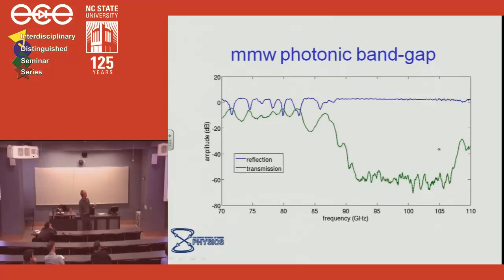Okay? This is a logarithmic scale. So that's as close to a perfect reflector as I can measure. And the transmitted field is down by 60 dB. And this is entirely due to multiple scattering. Okay? And the good thing and the bad thing about multiple scattering is that it makes everything incredibly sensitive to small perturbations. I don't have the plot with me, but if we did this, took out one quartz wafer from the middle, then you would create a big defect state right here that goes almost all the way up to 1. Okay? So multiple scattering can be fun, but it can also be pretty scary.